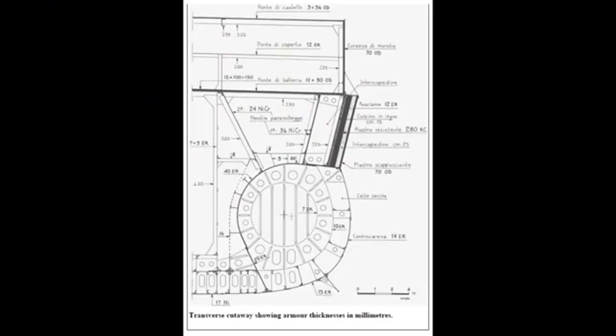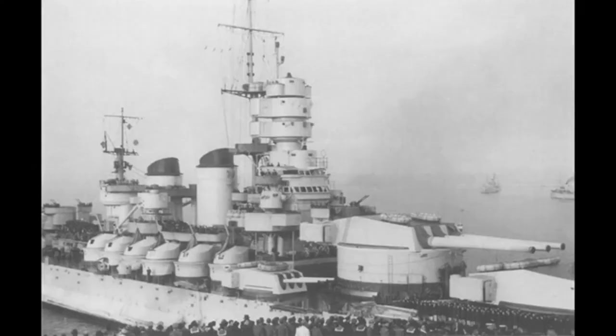Now, the Italians had their own way of going about things, which happily straddled the line. They varied the thickness of their hardened face depending on how thick the armour they were making. This gave their Terni plate a similar effectiveness to US Class A armour against cruiser-grade firepower, as at this overall thickness it had a very deep face-hardened plate. But this would transition to a thinner and more British level of face hardening at battleship grades of thickness, thus exploiting those factors as well for good resistance at the upper end of thicknesses of plate, as well as the better cruiser performance. Now, this has led some sources to classify Italian plate as the best overall World War II armour plate, as it scores well at both ends of the scale, unlike practically everybody else's.